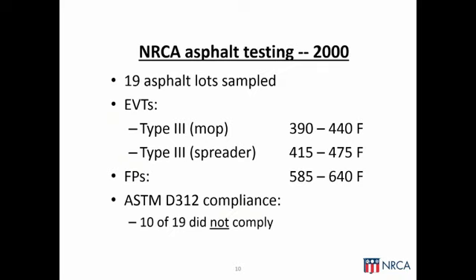But by 2000, we were actually measuring flashpoint temperatures on asphalt that we were getting out in the field as high as 640 degrees. So that's a relatively significant finding, because the rule of thumb in the industry at that point is you could heat asphalt in a kettle or tanker up to 25 degrees below its flash point. So if you have a 640 degree asphalt, conceivably that asphalt could be heated in the field up to about 615. The other significant finding from this 2000 study was that when we tested the asphalt samples that we procured, 10 of the 19 actually did not comply with the product standard ASTM D312 for asphalt. And that was a little bit startling for us.